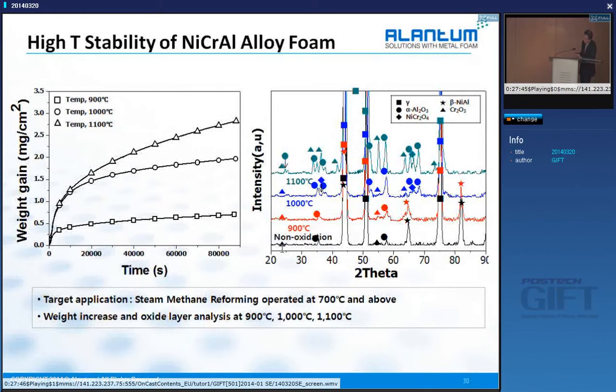That's the reason our target application, SMR, steam methane reforming, operates at 700 degrees and over. And you see oxide layer analysis at the higher temperature.